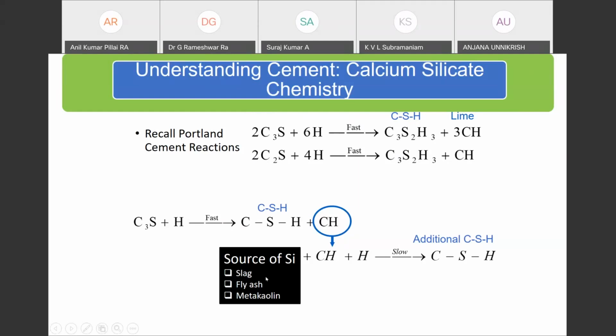And these are identified as slag, fly ash, metakaolin. These are all materials, especially slag and fly ash, that are waste materials coming from other industries. Slag is a waste material which comes about during the process of extracting iron from iron ore. And fly ash is what we get when we burn coal to produce electricity. It's the ash that is left behind. That is what we call fly ash. And both of these materials have silica in them. So when I have an extra source of silica, which I add to the cement, that silica is able to utilize the calcium hydroxide that is given off by the cement reaction, and is able to produce additional CSH. Basically, I produce additional calcium silicate hydrate.